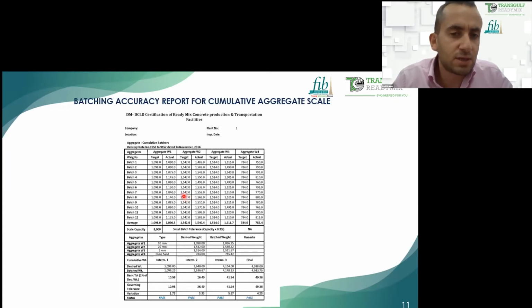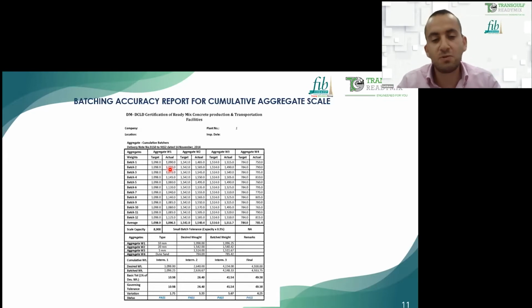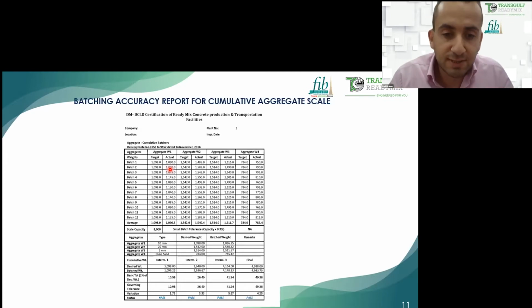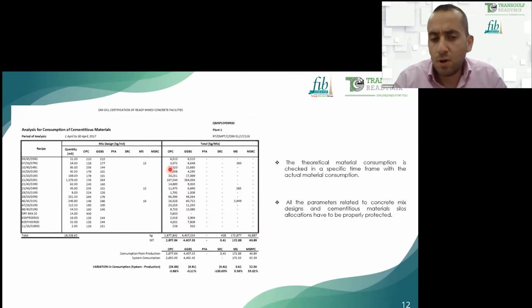And now this one is about the scales' accuracy. This is collected from the system: 10 consecutive batches, minimum 10 consecutive batches, and we verify the weights between target and actual. As an example, for the aggregates or for the cement, it's plus or minus 1%. So we verify it is as per the standard. One more step verified is the material consumption.